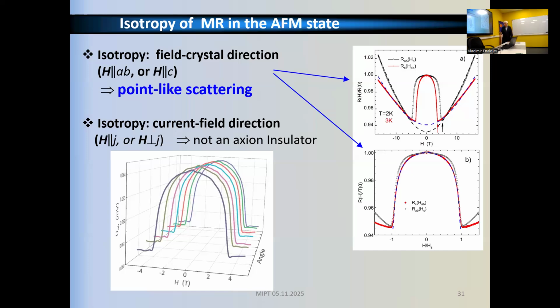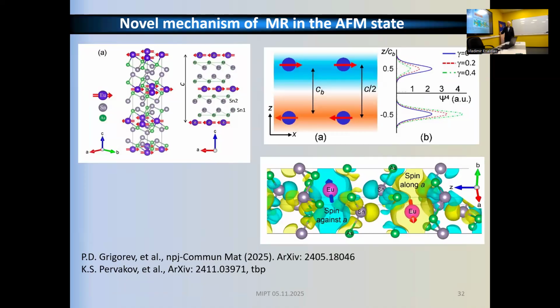So above the spin saturation field, there are no puzzles. Now, the mechanism which Pasha Grigoriev suggested is very simple. It is based on the fact that as you increase magnetic field, the electrons which have different spins relative to the europium atoms concentrate closer to the plane of europium, which they prefer. And this is shown here in some units I will explain later. As you increase magnetic field, the electrons with a given spin redistribute from this to this band in real space. And this is also shown by the result of DFT calculation that shows that electrons with certain spins are located closer to either this or this layer.